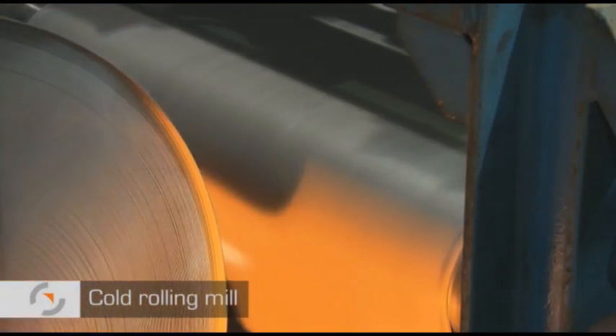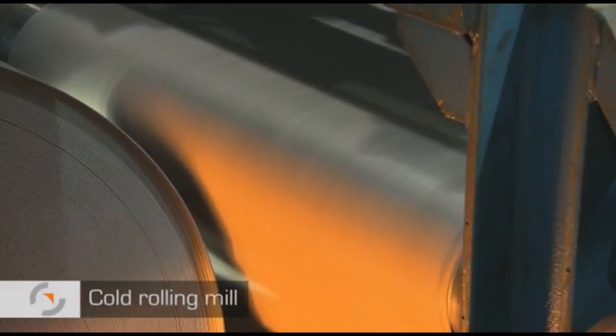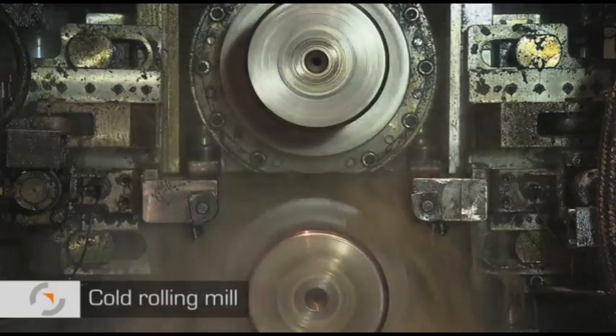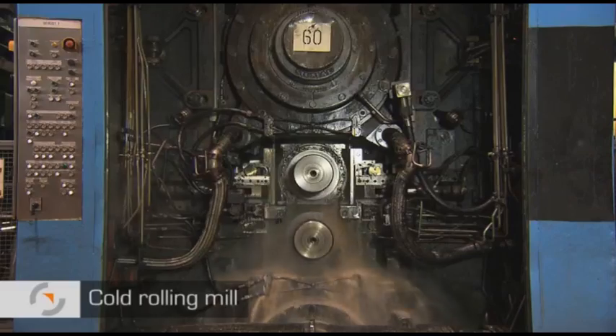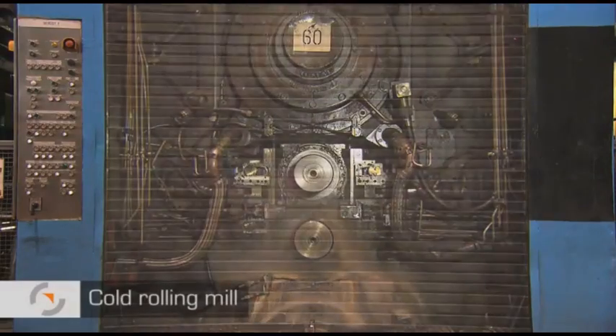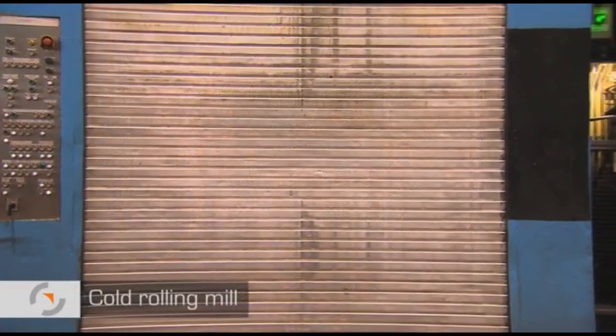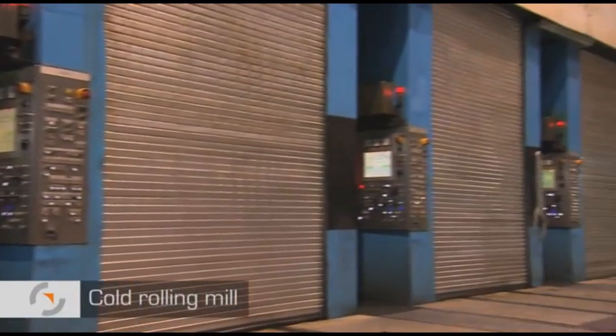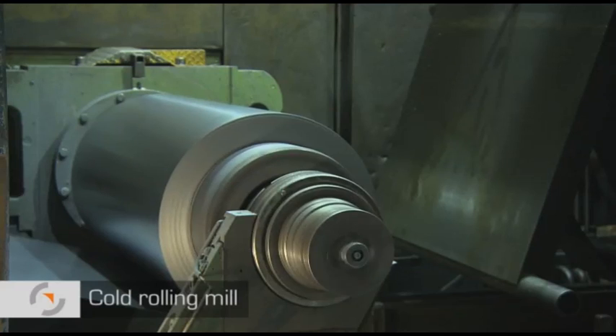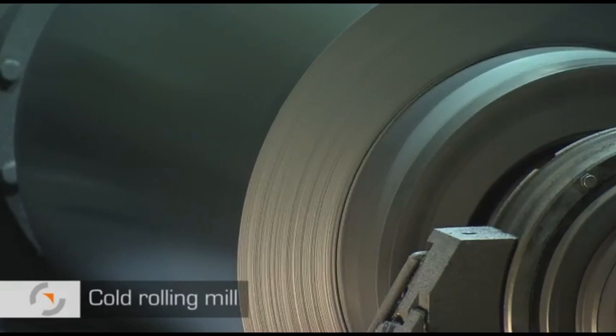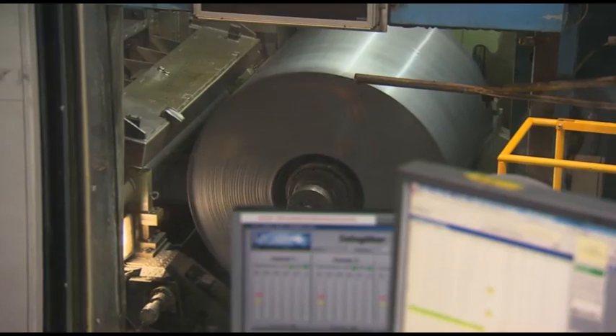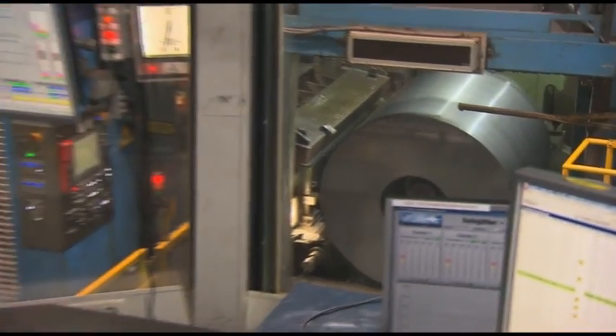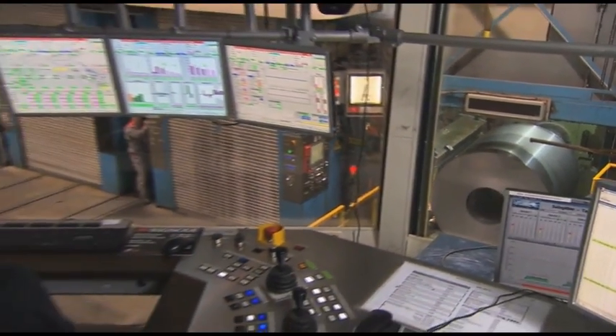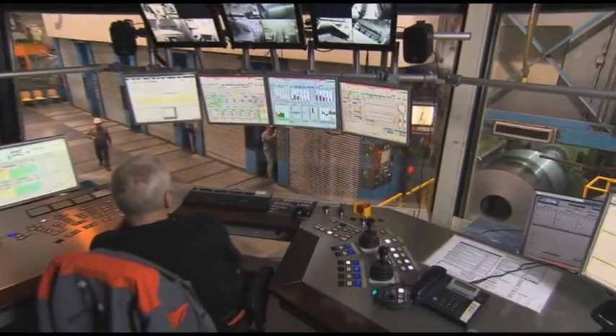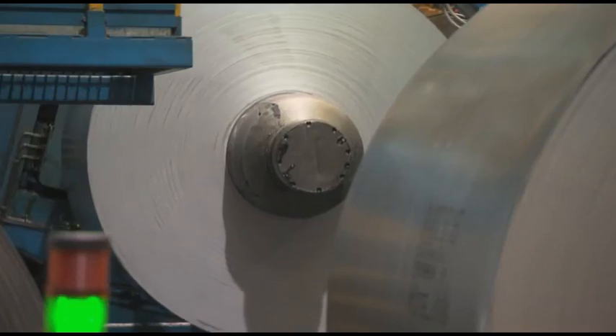Sheet thicknesses of less than 3 millimeters are produced in the cold rolling mill. The central section of the cold rolling mill is the 5-stand tandem mill. The pickled strip is rolled in a single pass to finished thicknesses of between 0.35 and 3.0 millimeters according to customer specifications. At this stage, final rolling speeds of up to 90 kilometers per hour are achieved. A process computer processes the measured data obtained from the entire rolling train and controls the rolling process.